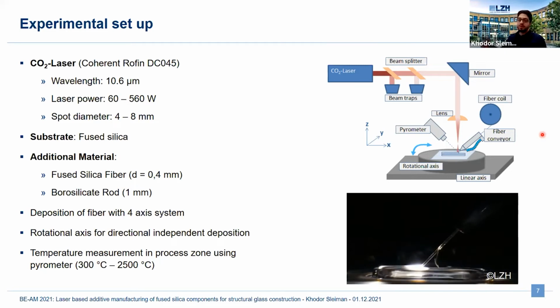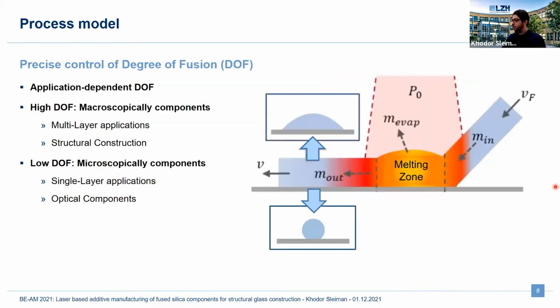So the fiber gets deposited onto the surface of the substrate, and through a 4-axis system, we can deposit the fiber continuously and in complex shapes, because through the rotational axis, we gain direction independence. Yeah, and the temperature in the process zone is measured through a pyrometer, so we can precisely control the contact angle and the degree of fusion of the glass fiber.